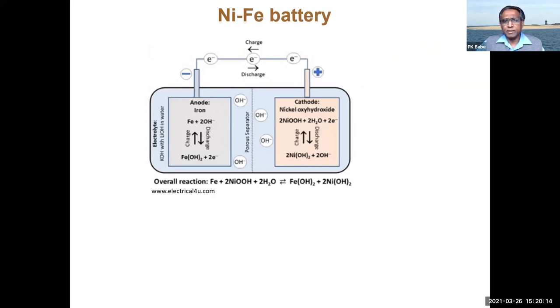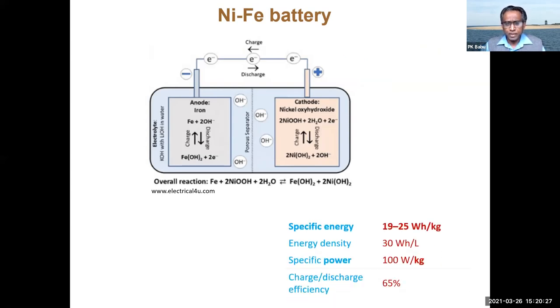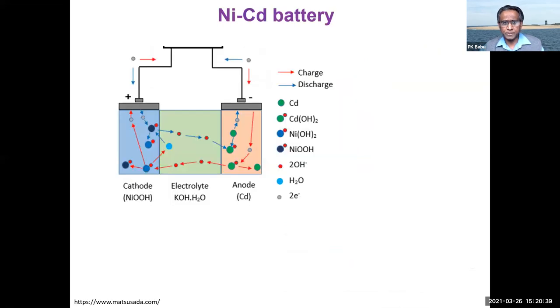Nickel iron battery has the iron anode. Nickel in the form of nickel oxyhydroxide was used as the cathode for this. This battery has the following characteristics. Energy density is low, just about 30 watt hour per liter. Charge discharge efficiency is about 65%.